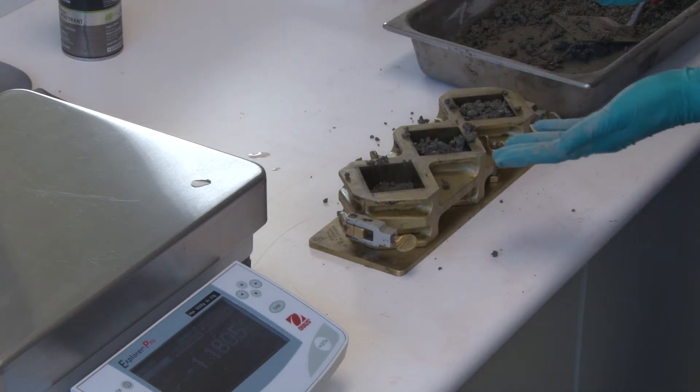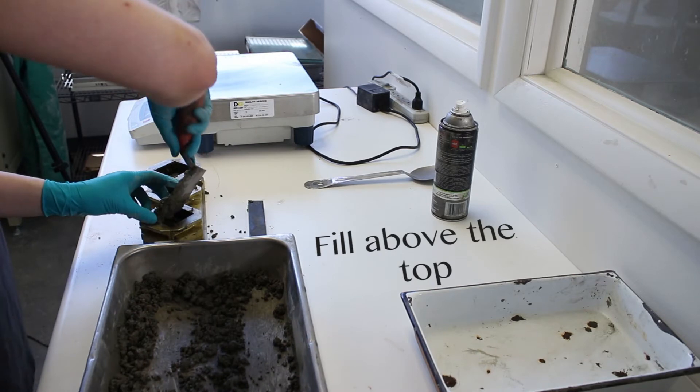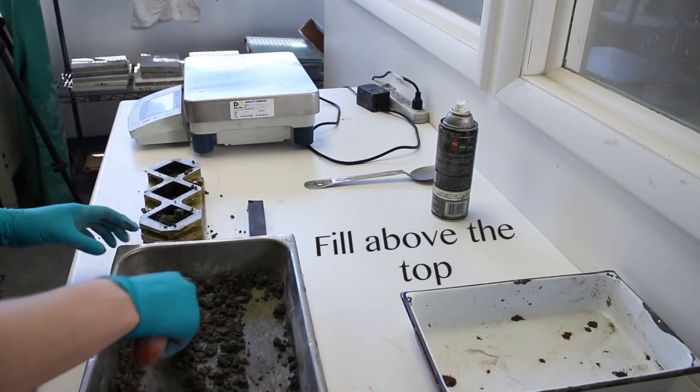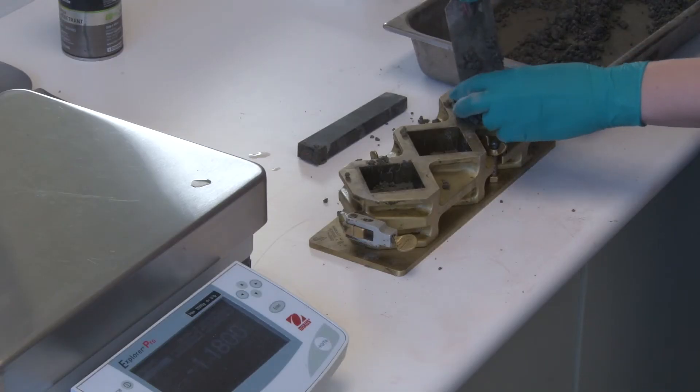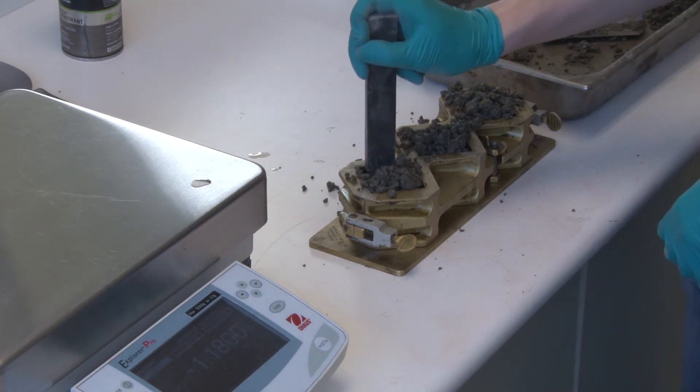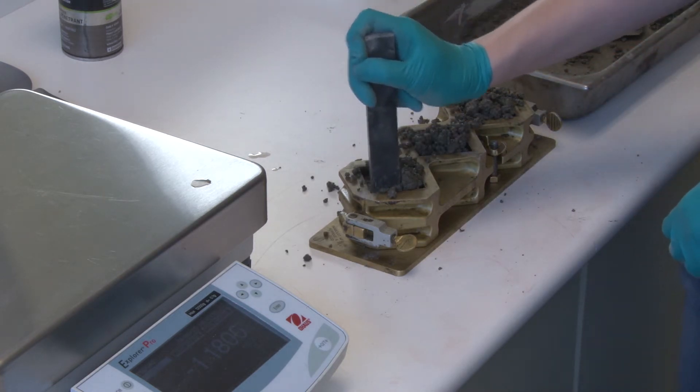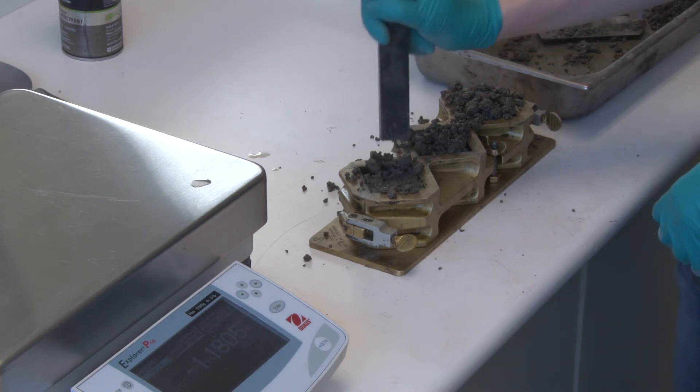And you will see now it is compacted to hopefully half the inch height. The previous time was 16 times total of pushing down. Again, it is 16 total, making it 32 for the entire cube.